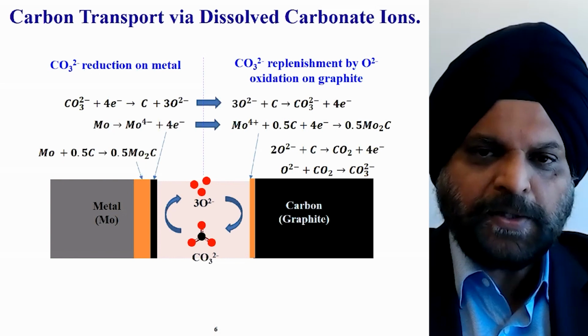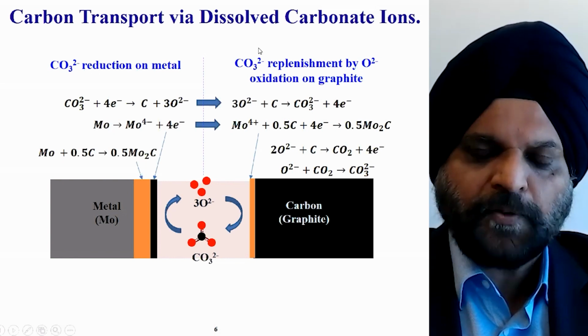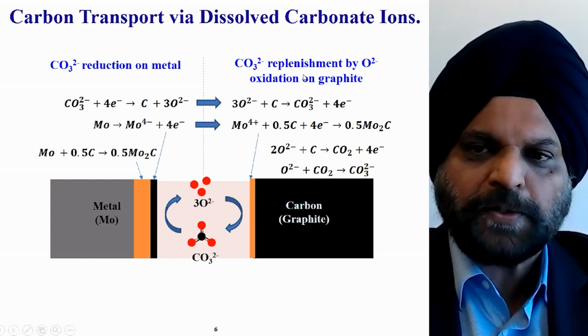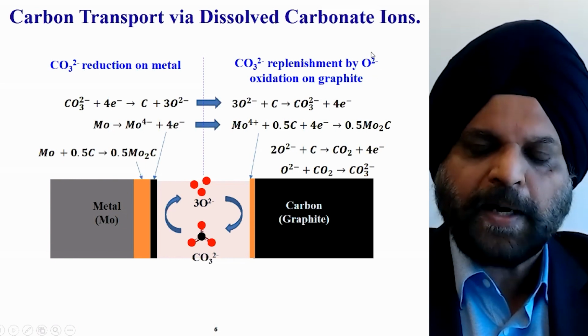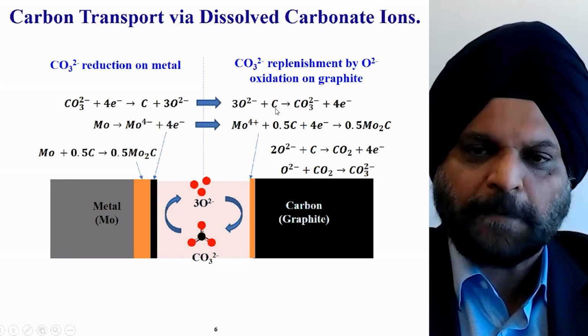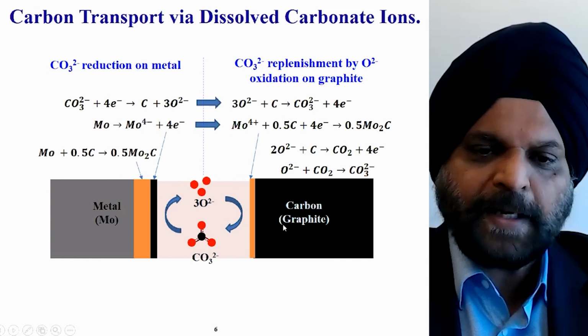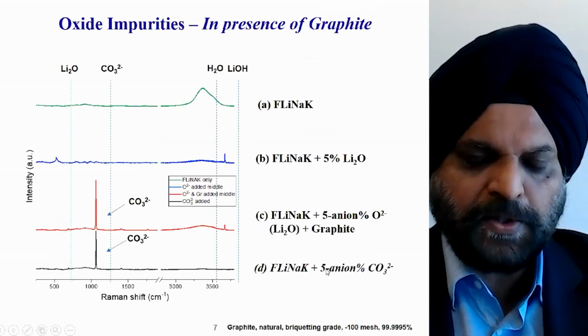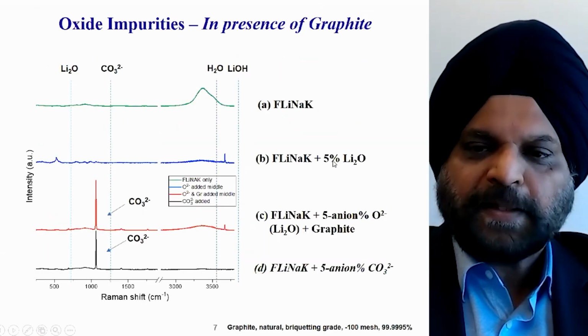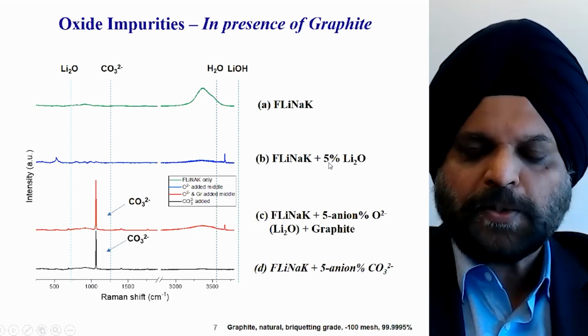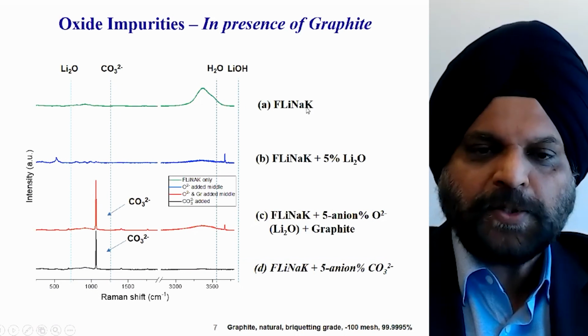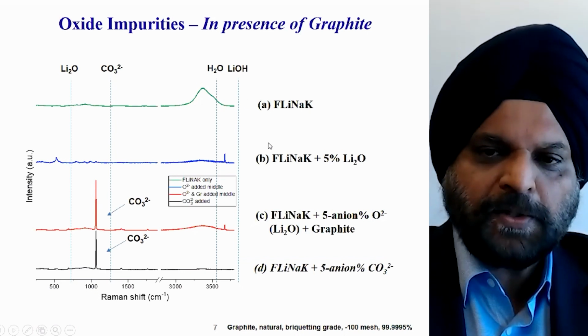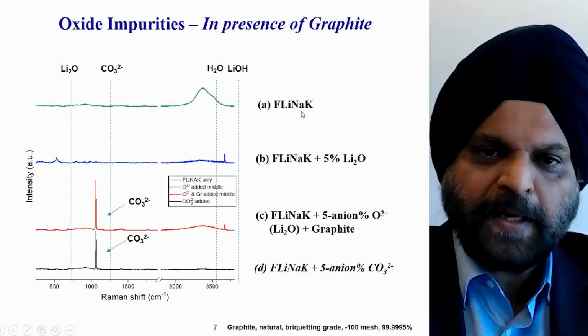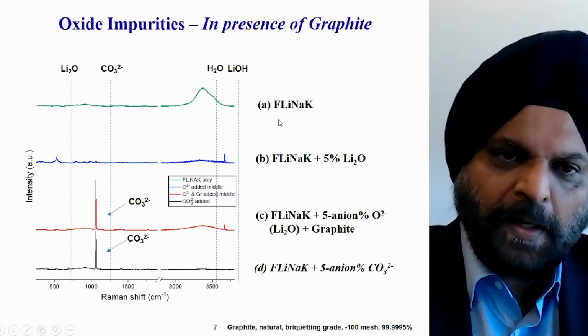So this can continue, and you don't have to have carbonate in your salt. You can actually produce carbonate by reaction of oxides with carbon, giving you this mechanism that we have proposed and shown. To prove that this is possible, we took some FLiNaK, and what you see here are Raman spectra. So if you take just FLiNaK, this is the Raman signal.